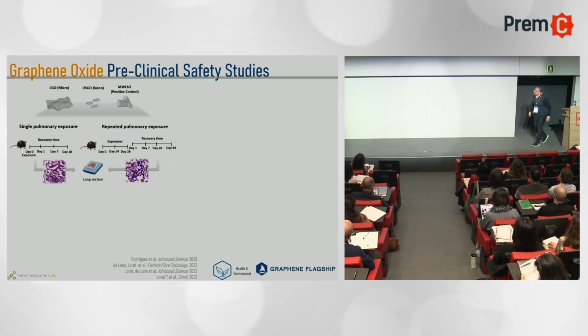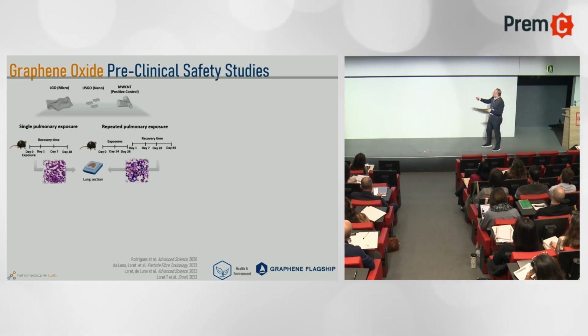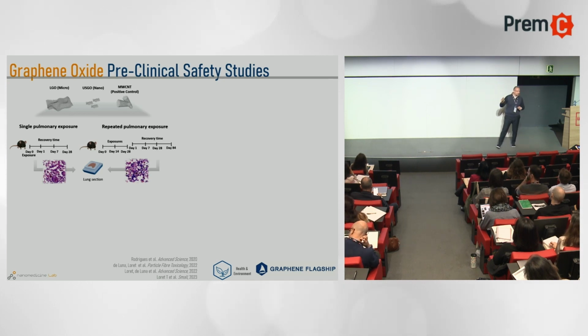The second thing we invested time and resource on was to go through a very thorough preclinical study pipeline. So we pushed the materials through in terms of identifying our limitations using animal work. A typical study platform is shown here. So we had our graphene oxide materials. In this particular case, I'm showing you one example. We compared large graphene oxides and ultra small, so the extremes of our lateral dimension variability. And we compared that to multi-walled carbon nanotubes, the type that was carcinogenic, the type that the regulators didn't like. So that was, if you wish, from a toxicological safety point of view, our positive control. And we compared everything else against those multi-walled nanotubes.